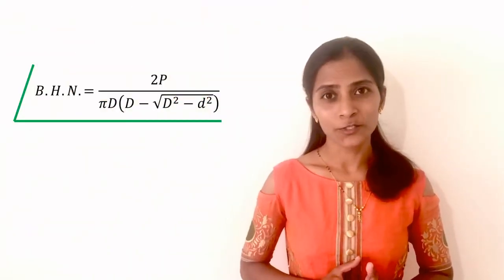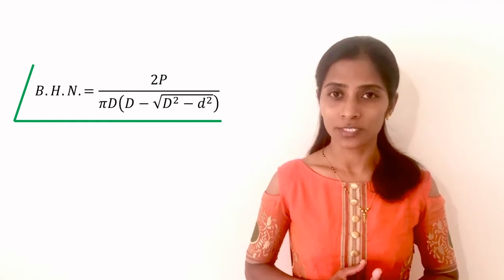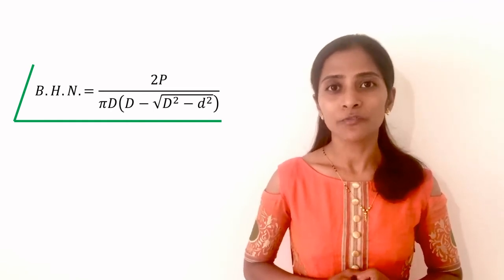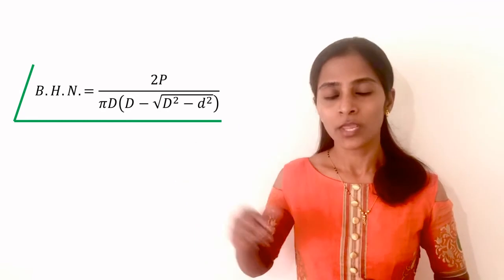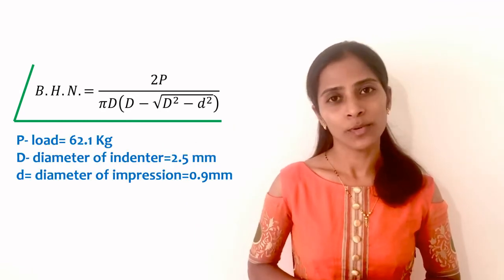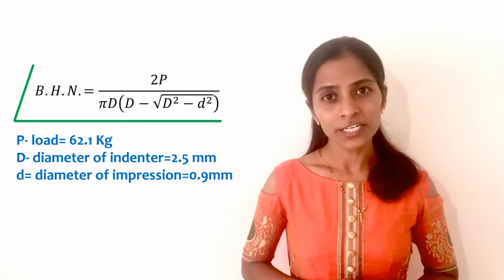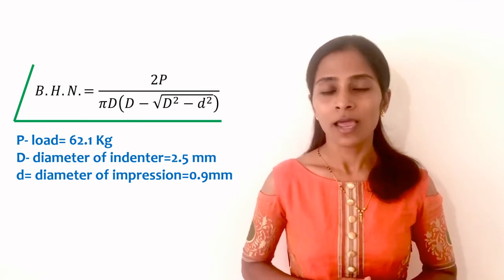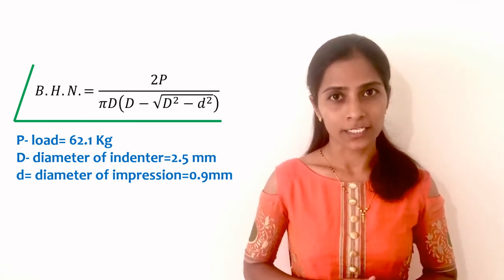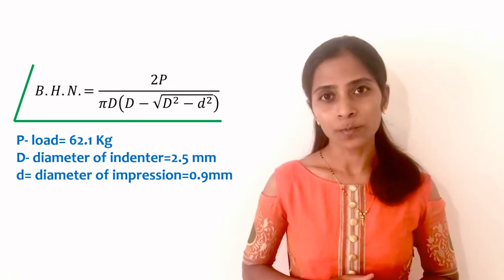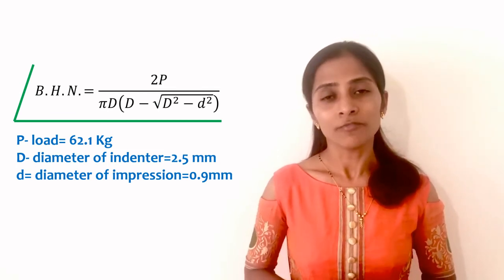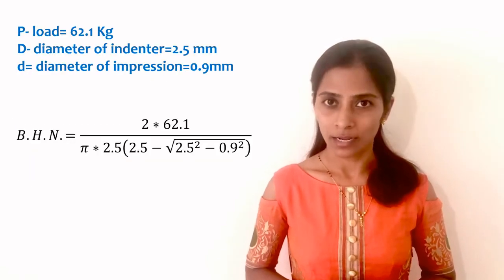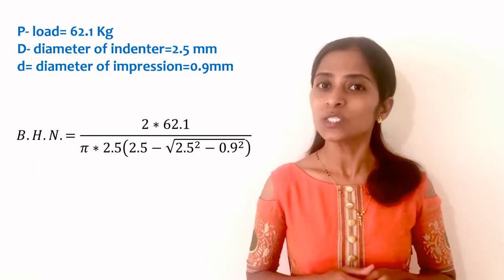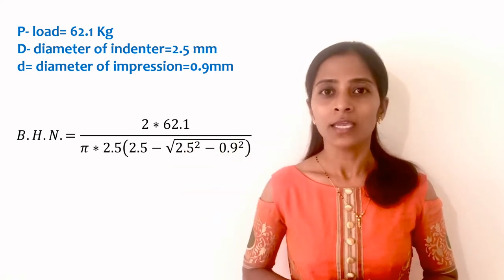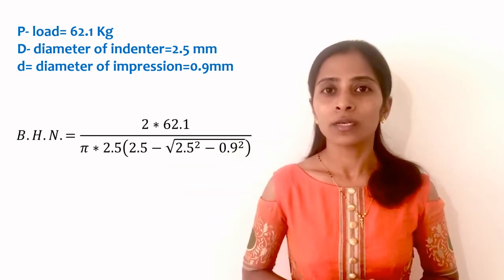To calculate the hardness of the given test specimen by using the non-standard Brinell hardness test, we use the formula which I have displayed over here. During this test, I have used aluminium as a test specimen, a ball indenter of 2.5 mm diameter and a load of 62.1 kg. With these parameters, I have obtained an impression on the test specimen which has a diameter of 0.9 mm. Now, I am going to put these values in the formula and then it will give me the hardness of the aluminium test specimen, which is approximately 94 BHN.